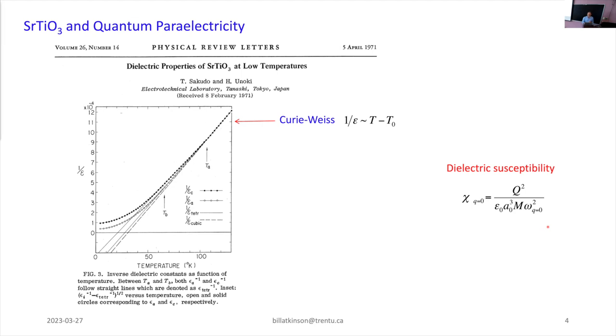And as you lower the temperature at high temperatures, you're getting this linear temperature dependence. Right? The phonon frequency is going down as you reduce the temperature, and it's following a Curie-Weiss law. So T naught in this expression here, that is the temperature at which you anticipate a mean field transition to the ferroelectric phase. That's where your ferroelectric susceptibility diverges.